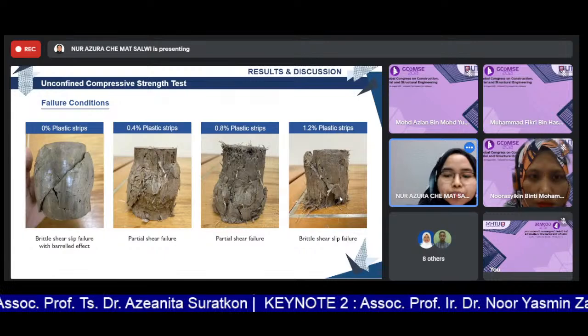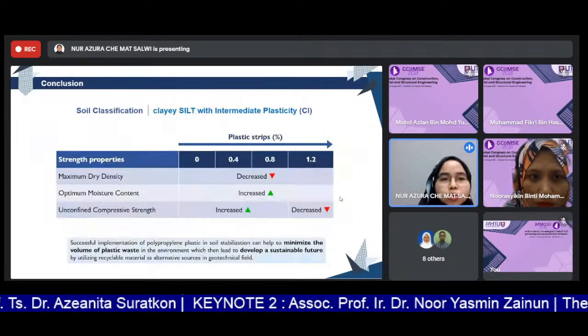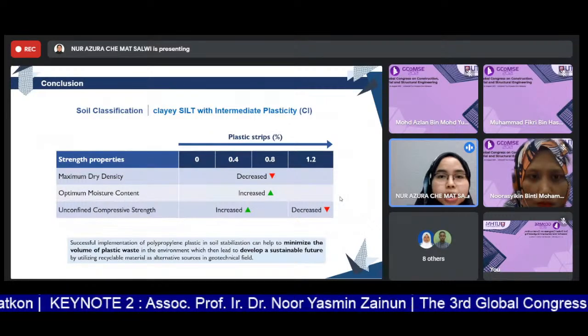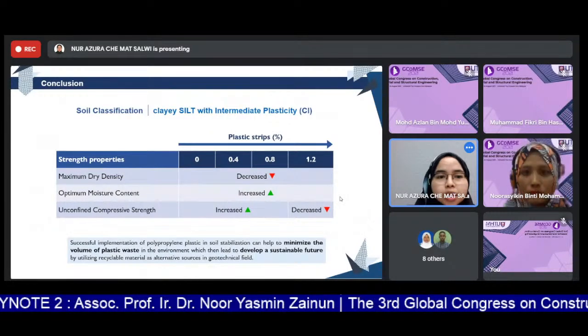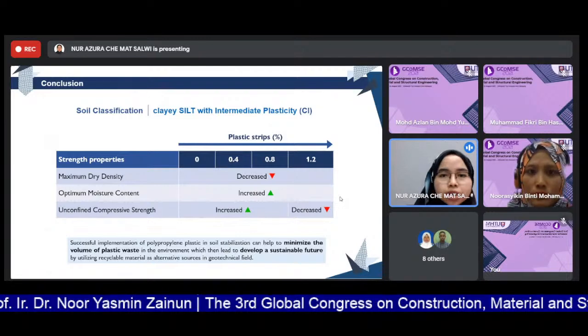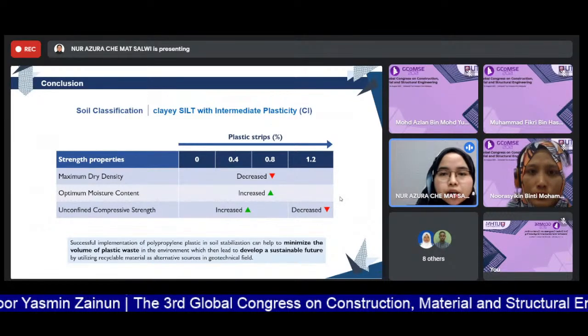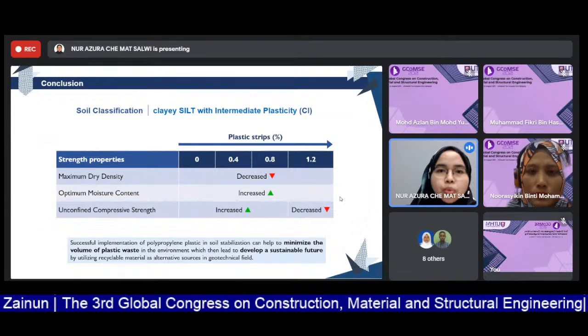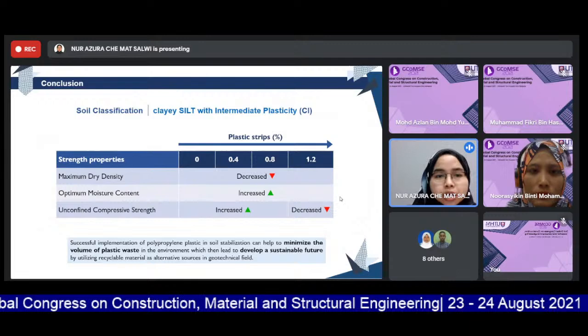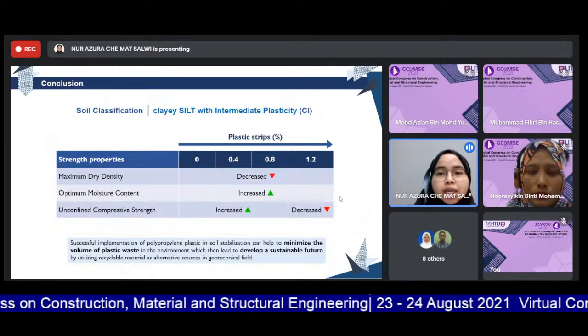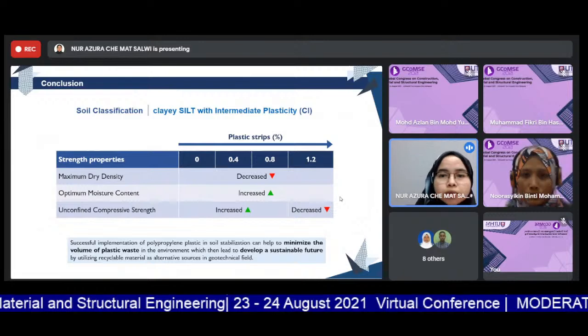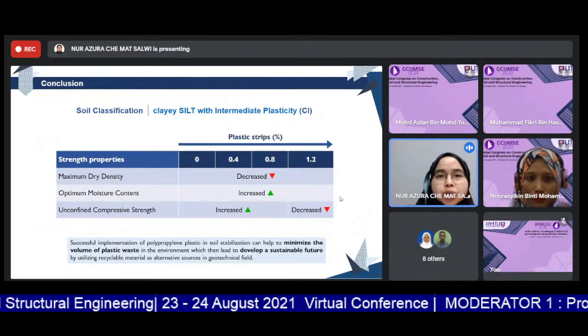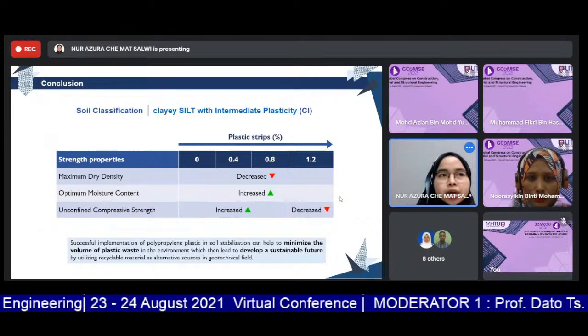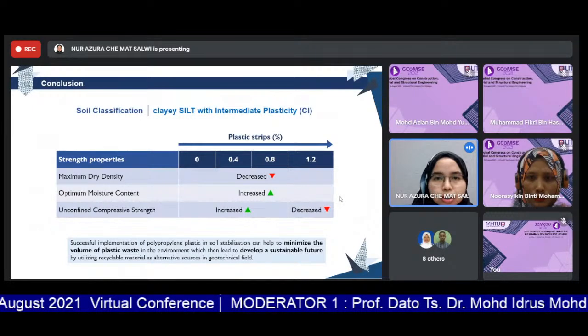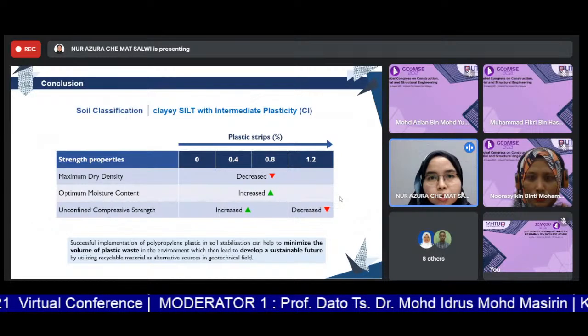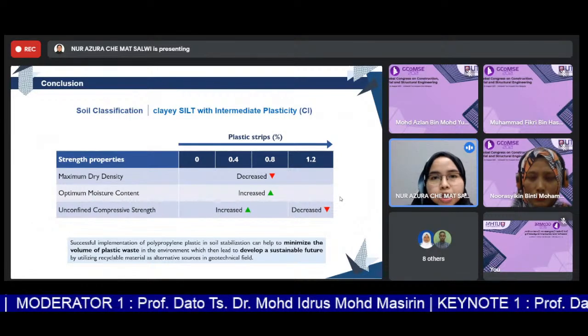As a conclusion, the soil sample is classified as clayey soil with intermediate plasticity. The maximum dry density decreased while the optimal moisture content increased as the percentage of plastic strips increased from 0 to 1.2%. Meanwhile, the unconfined compressive strength initially increased up until addition of 0.8%, but then eventually decreased at 1.2% of plastic replacement. Hence, the optimal percentage of polypropylene clamshell food container strips that can be added into soil was found to be 0.8% by weight of dry soil.